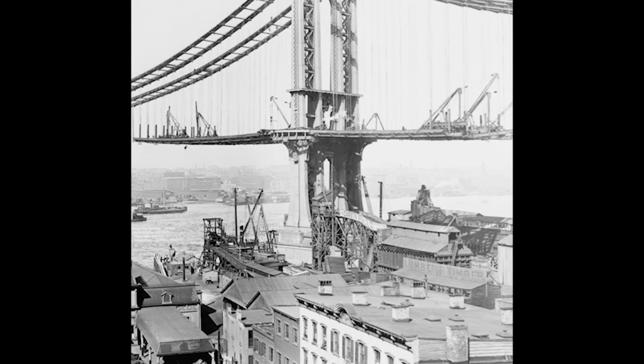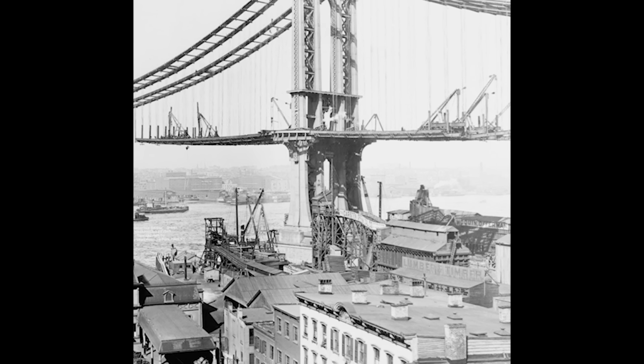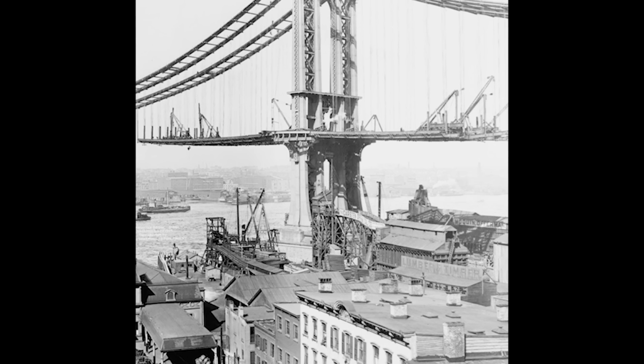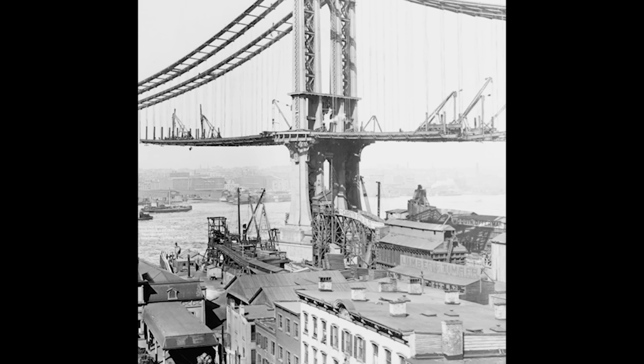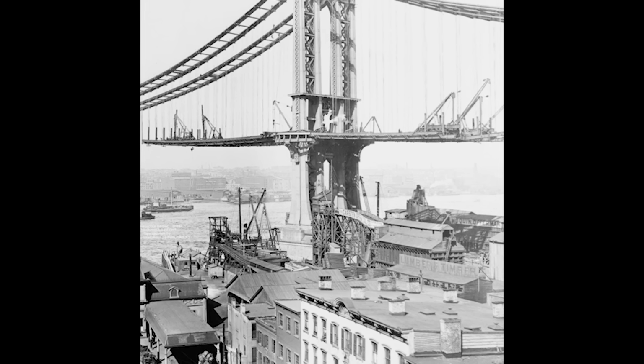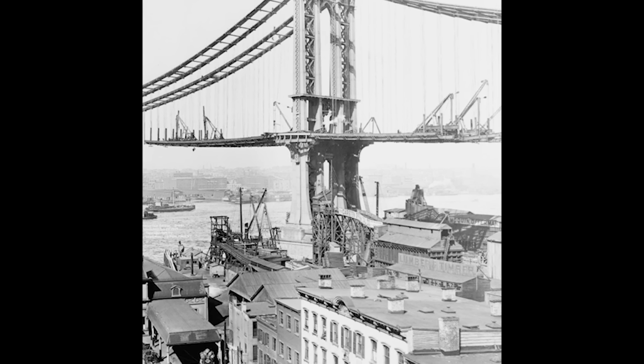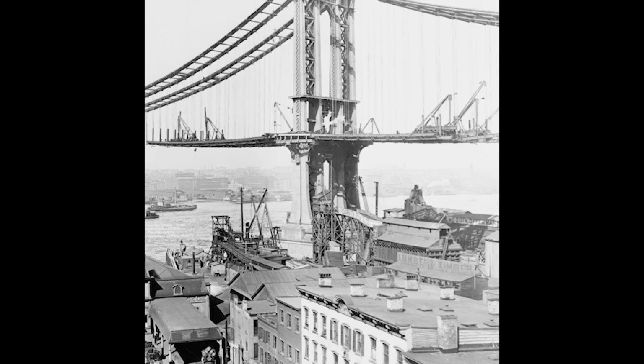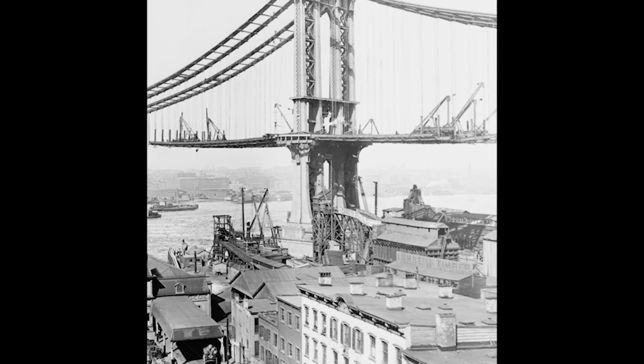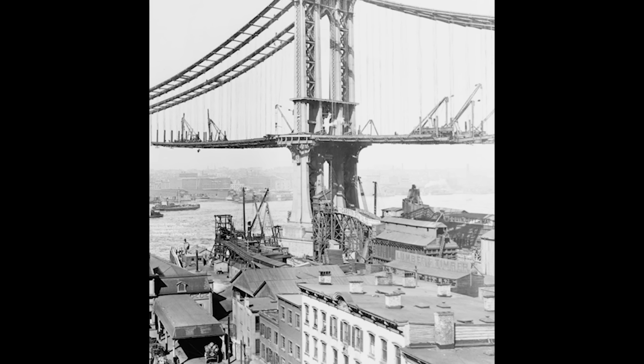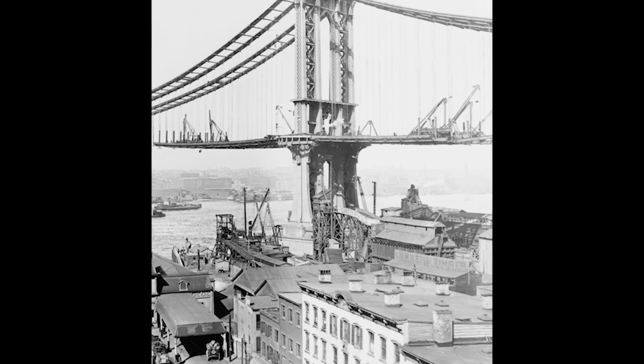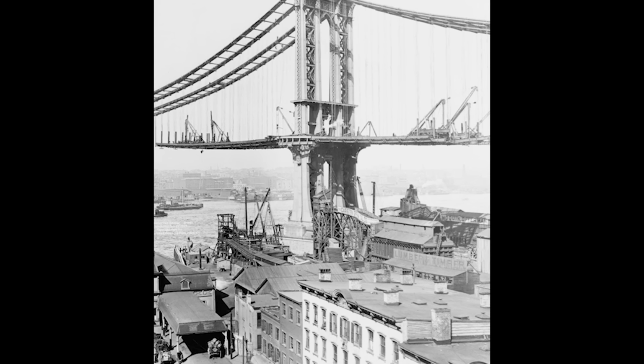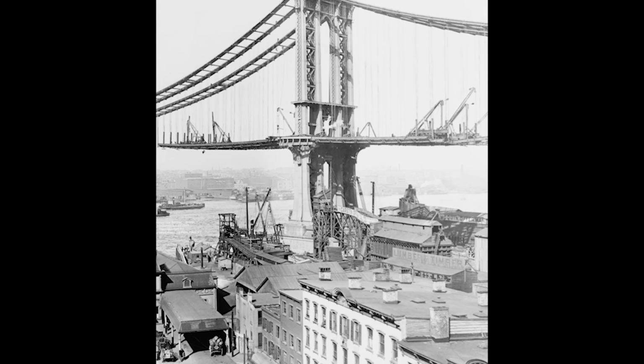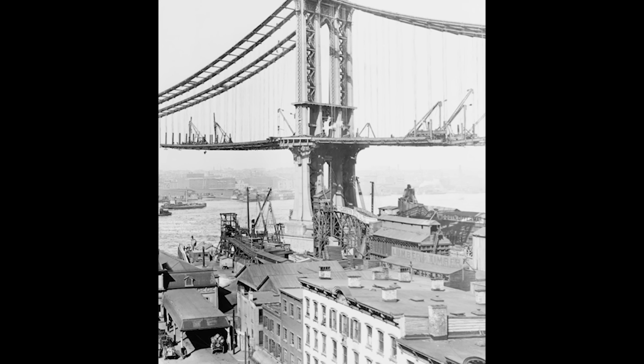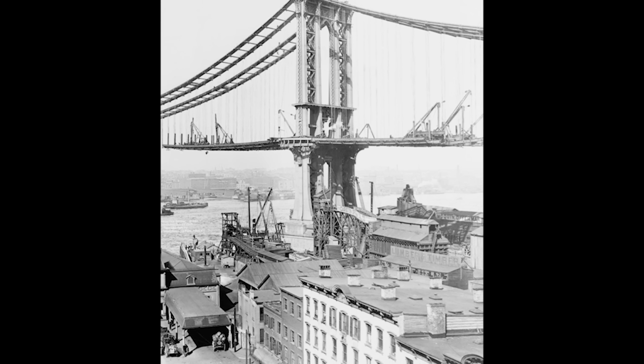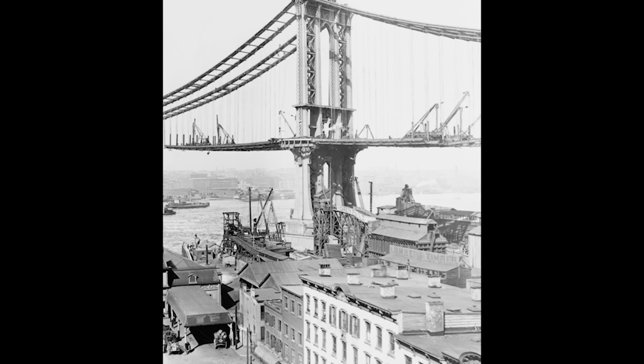The cable began to resemble a sealed pressure vessel designed to exclude moisture and atmospheric contaminants from the galvanized steel within. The overlapping protective barriers created redundancy that could survive the failure of individual components while maintaining overall system integrity. Even if the outer paint developed cracks, the red lead paste would continue providing chemical resistance. Even if the paste deteriorated, the galvanized wrapping wire would maintain physical protection. Even if the wrapping wire corroded, the galvanized structural cable would sacrifice its zinc coating to protect the steel substrate.